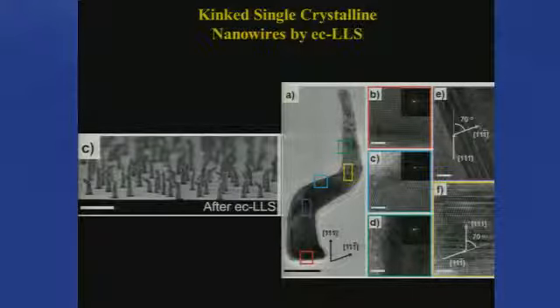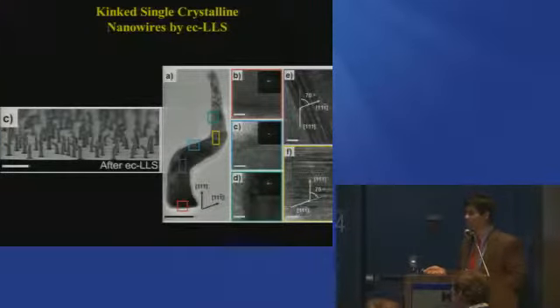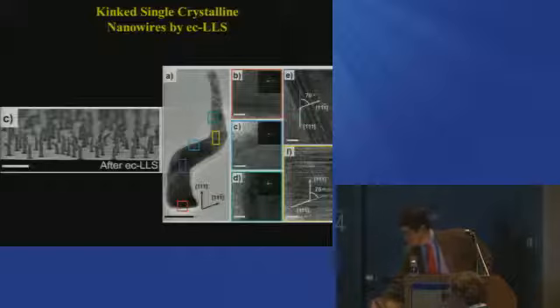And if you look at all pieces of this, you can track out this being one single crystal. But there's something about how when this crystal grows that causes the direction to slightly change. The interesting thing that we still don't know is that if you look uniformly across this whole array of thousands of wires, whatever that factor is that causes this crystal growth change, it occurs simultaneously at all of these. So it's a function of something about the process, which we are still trying to figure out.